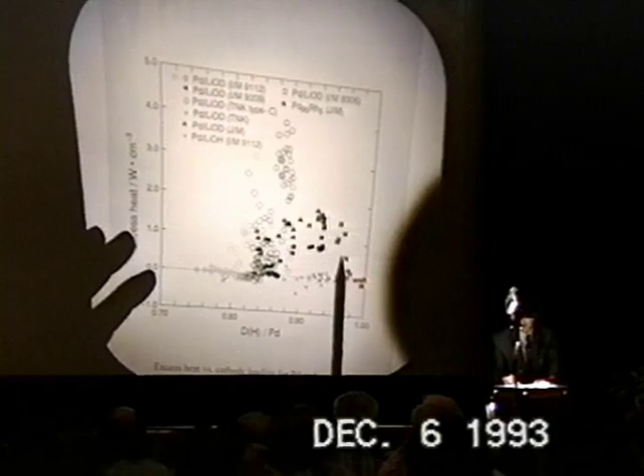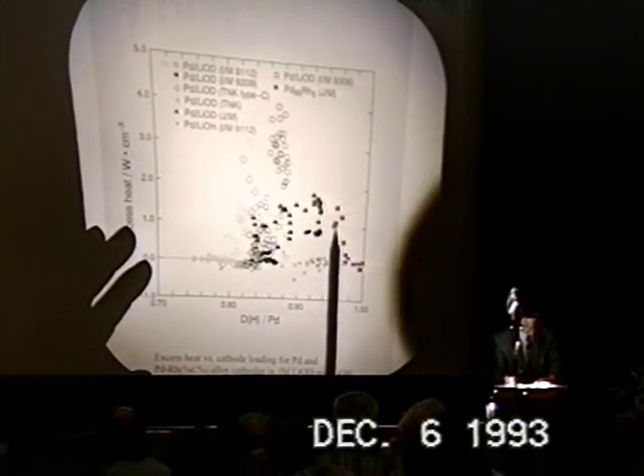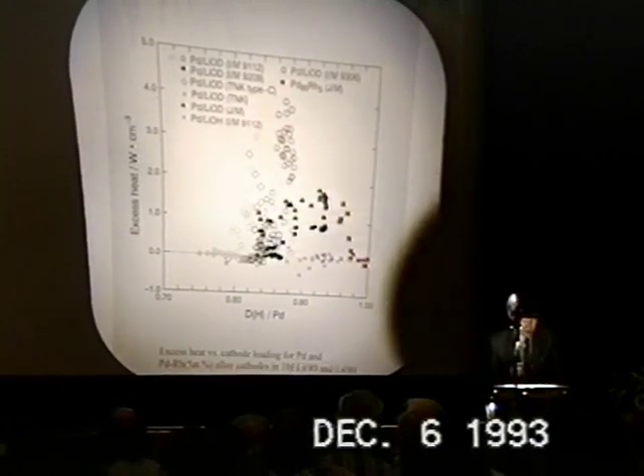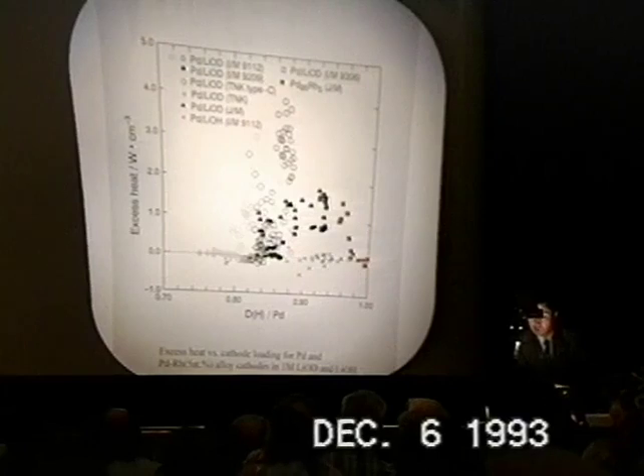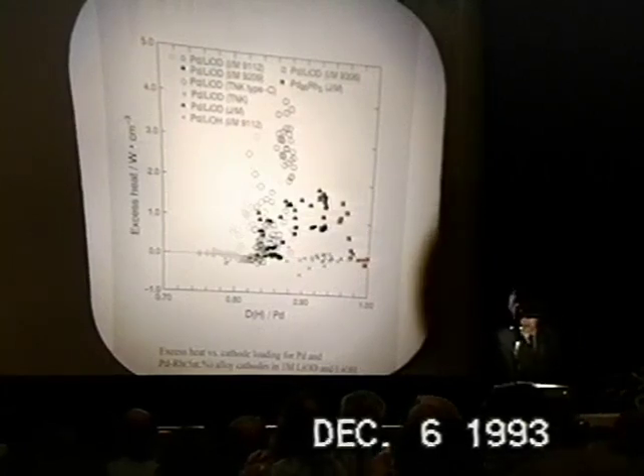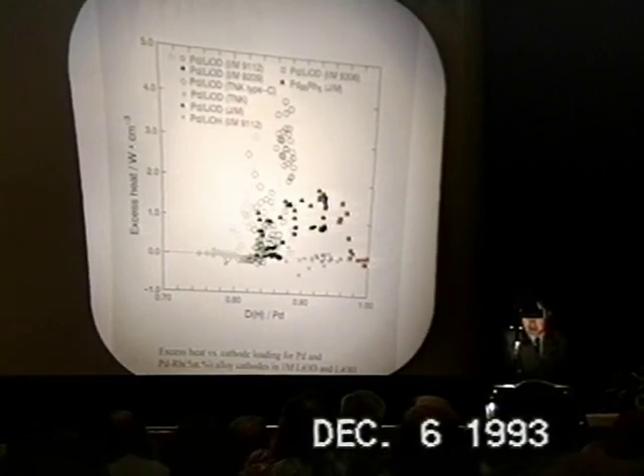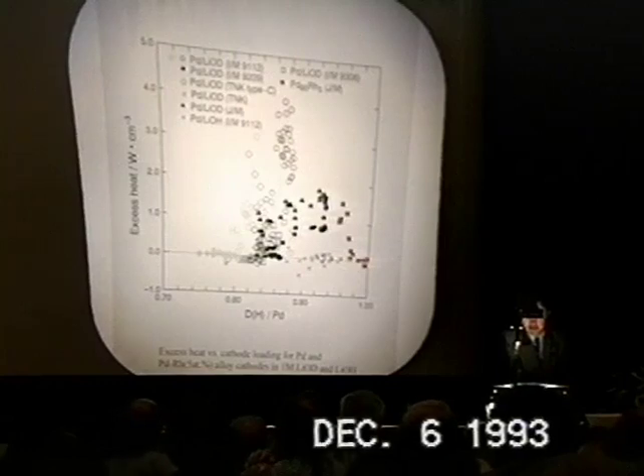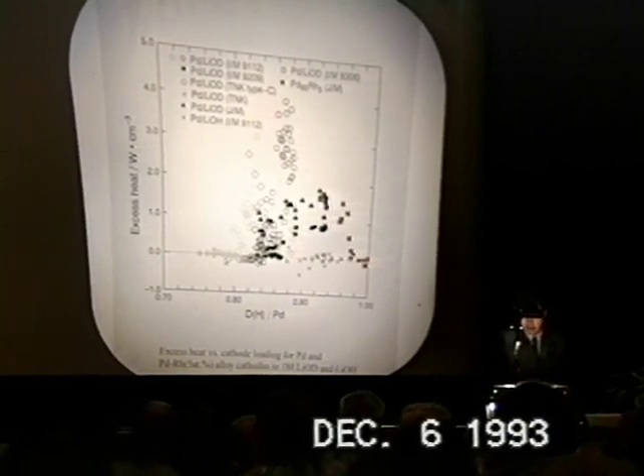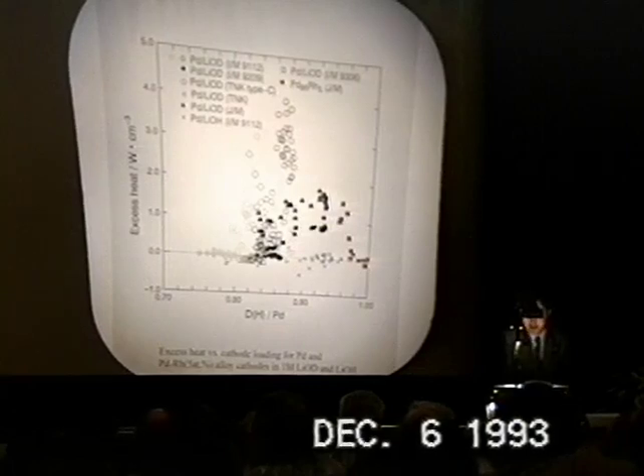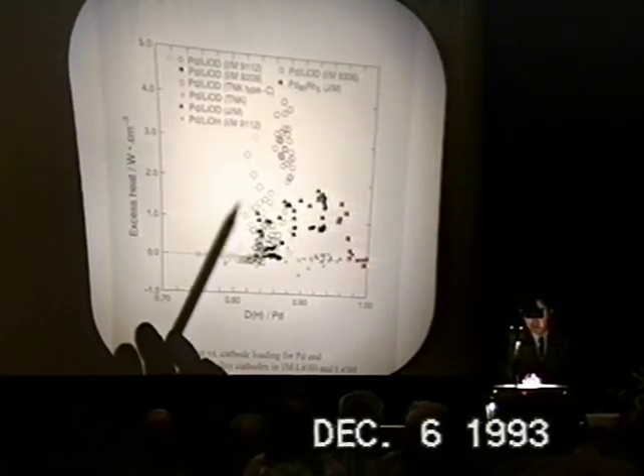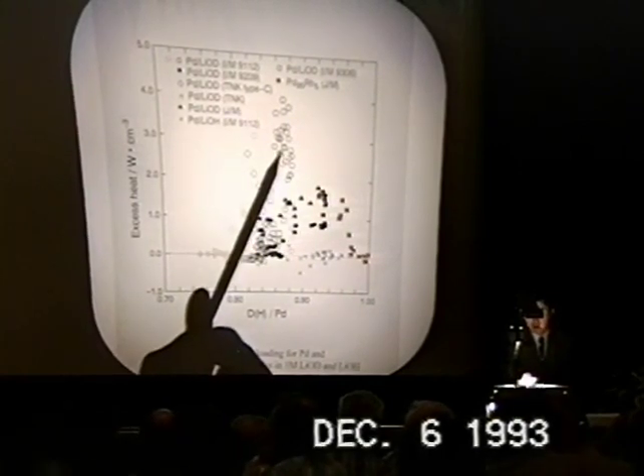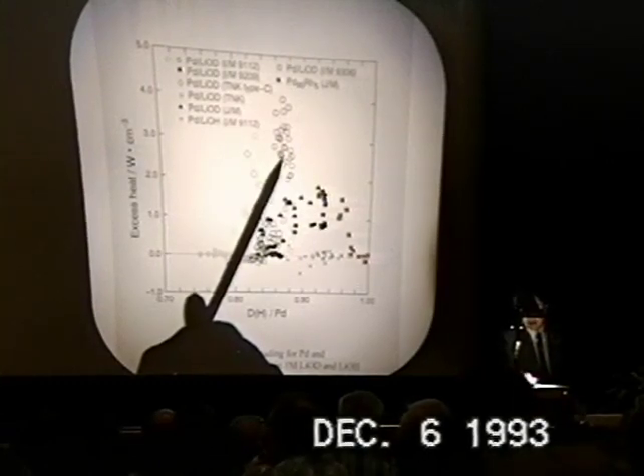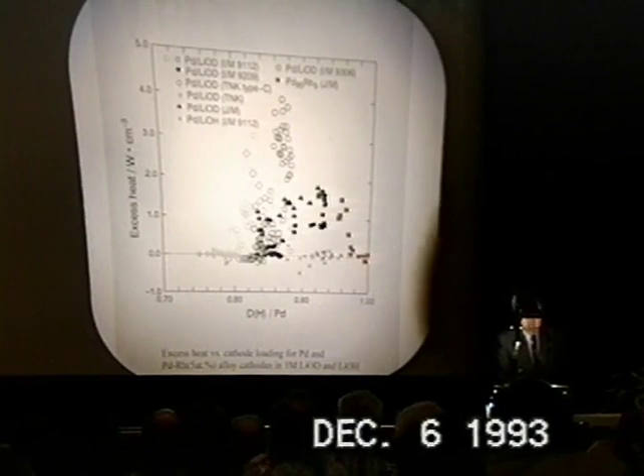So, to summarize all the data, including the data using 5% loading palladium alloys, we have this excess heat as a function of deuterium loading ratio. If we look at this data, we are not sure if deuterium loading ratio is a very important factor after some certain value, partly because of the accuracy of our measurement, the data points are very scattered, and we still do not understand why this palladium gave much higher excess heat compared to other palladium materials.